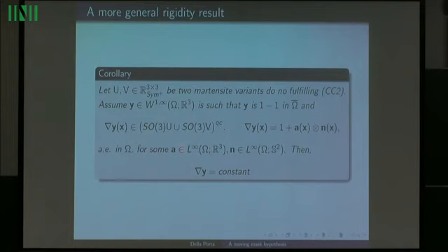Convex integration here could give you many possible microstructures, but thanks to this differential constraint that we obtain from our moving mask hypothesis, we can deduce that if the cofactor conditions are not satisfied, then two martensitic variants can form just a constant deformation gradient, so an average constant microstructure.